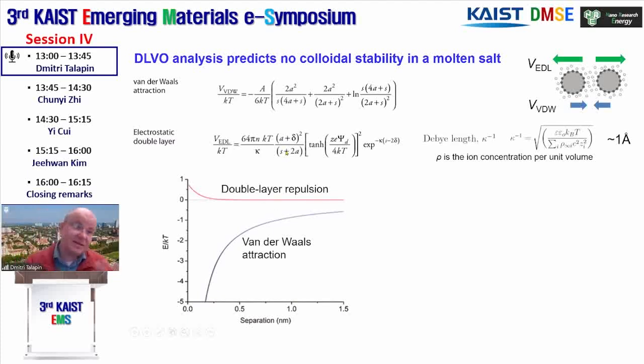And that typically looks at this class of theories known as Derjaguin-Landau-Verwey-Overbeek analysis and its extensions, which typically compares van der Waals attraction to electrostatic double-layer repulsion. But the problem with molten salt is that it has such a high ionic strength, or such a high polarizability, that the electric field cannot extend beyond like 1 or 2 interatomic distances. So the Debye screening length is on the order of 1 angstrom, which doesn't make sense. Pretty much, this analysis doesn't make sense at these length scales.